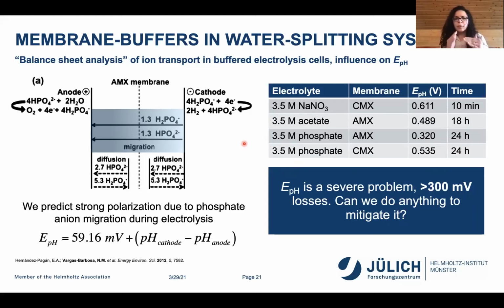At the time we were able to say, okay, well, the electrolysis cell is not running all the time. So we did on-off cycles, on for 8 hours, off for 16 hours. And this helps a little bit with the pH gradient, because while it's off, you have generated enough of a concentration gradient that it really drives the diffusion in the opposite direction. So it really helps compensate it. But during the time that it's running, it can polarize quite significantly. And it doesn't fully reverse. The time it takes to really go back is very slow. So it was a really big problem, and we started thinking, can we do anything to mitigate it?